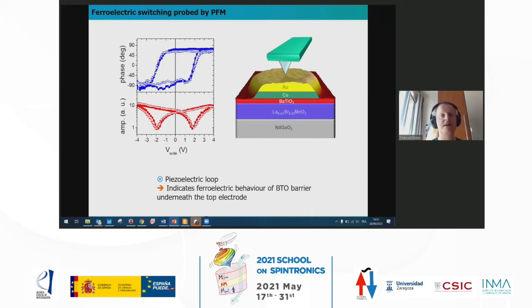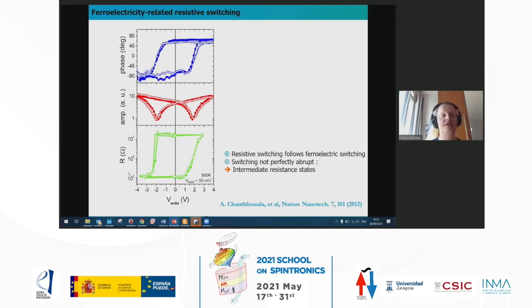So here, this is PFM, so piezoresponse phase and amplitude loops, which confirm that the barium titanate below the top electrode is ferroelectric. And then we can measure the resistance as a function of the voltage that we apply to the junctions. We apply voltage of different amplitude, and in between we read the resistance level with a small voltage of here 50 millivolts. And you see that we have a large hysteretic dependence with two extreme resistance states that are different by more than 2 orders of magnitude. And in some devices, we have a difference of up to maybe 4 or 5 orders of magnitude. So we have a confirmation of this tunnel electroresistance effect in the solid state devices.